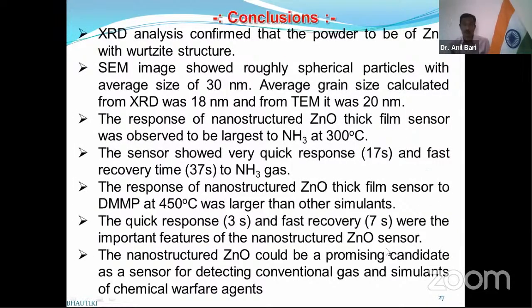Now, finally, conclusions. The XRD analysis confirmed that the powder is ZnO with wurtzite structure. The SEM image showed roughly spherical particles with an average size of 30 nanometers. The average grain size calculated from XRD is 18 nanometers, and from TEM it was observed to be 20 nanometers. The response of the nano thick film sensor was observed to be largest to ammonia at 300 degrees centigrade. It shows quick response, 17 seconds, and fast recovery, 37 seconds, for ammonia.